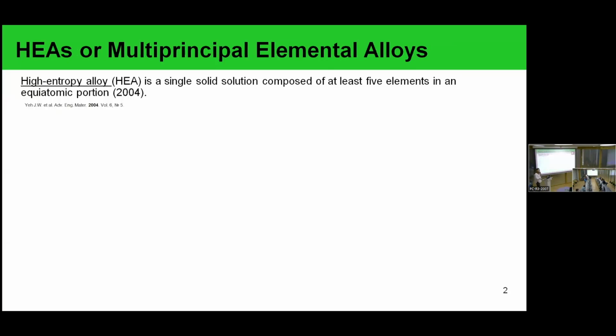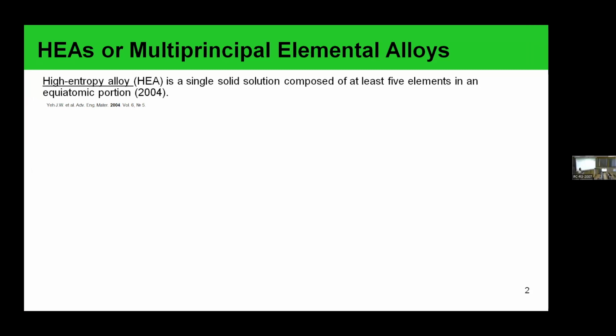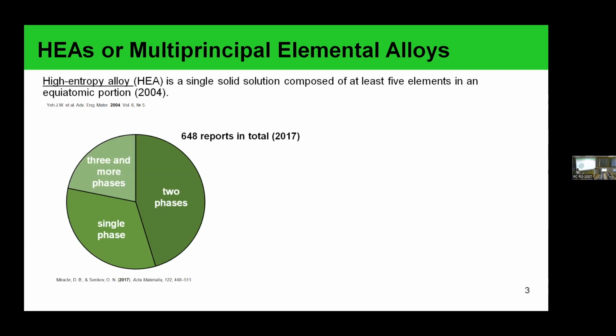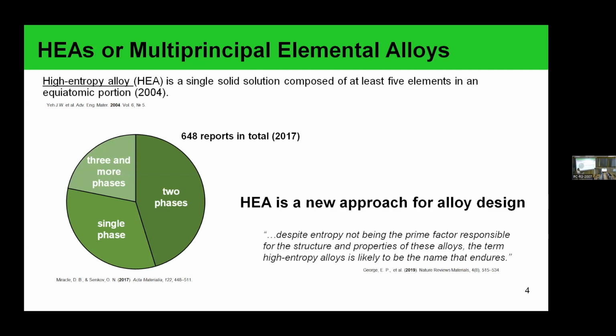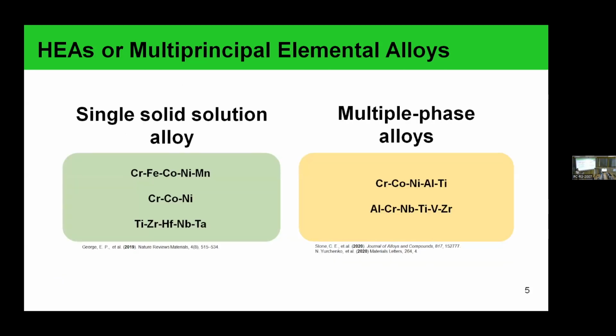Starting from the definition of the high-entropy alloys, they were first published in 2004. And according to the general definition, these are alloys which are a single solid solution composed of at least 5 elements in equiatomic proportion. But according to the reports reviewed in 2017, there are more than 600 reports demonstrating that these high-entropy alloys contain at least two phases. And today, the high-entropy alloys are considered mostly as a new approach in alloy design rather than a strict definition. Anyway, today there are several compositions which can be considered the most prospective. They can be divided into two groups: single solid solution and multi-phase alloys.